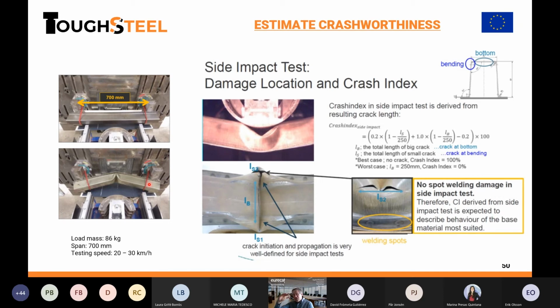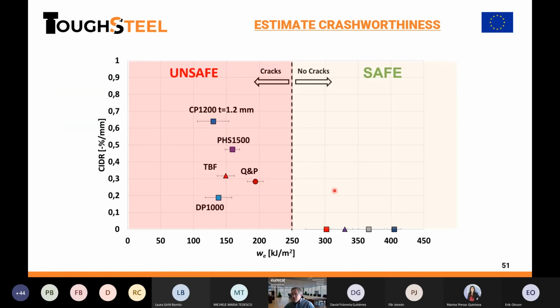The same for bending. We did it. The last slides were about axial crash. This is bending. You see here a beam that has been impacted by this catapult, in these conditions, and we have a crack. Here the crash index is calculated following this. This is in the presentation you will have, you can explore this in detail. But at the end, what is relevant is the crash index. Here again, at this value of 250, we see the border between materials that have no cracks after bending impact and the materials having cracks at bending impact. So safe regime, safe area, higher toughness; cracking materials, not enough toughness for bending.